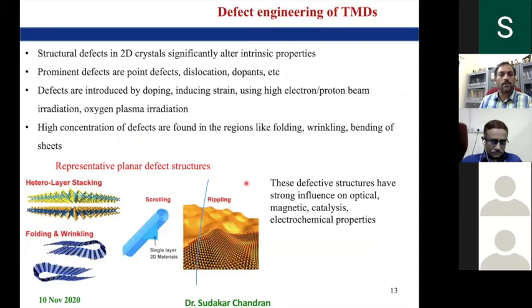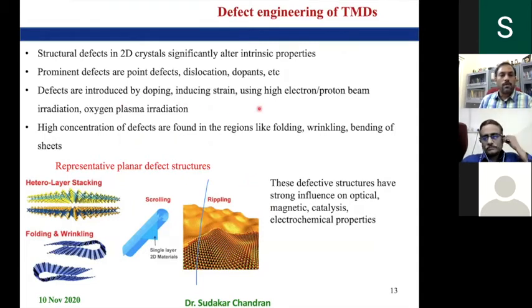2D kind of defects. In fact, these kinds of defects can be introduced into the system either by doping or by bombarding the sheet with high energy electron or proton beams or oxygen plasma irradiation and so on. So a lot of systematic studies are being explored to study how these defects can alter the optical, magnetic, and other functional properties.